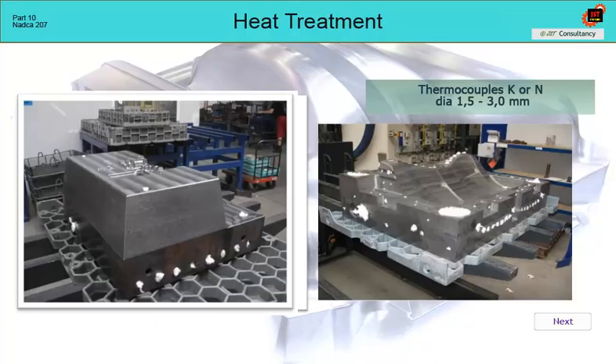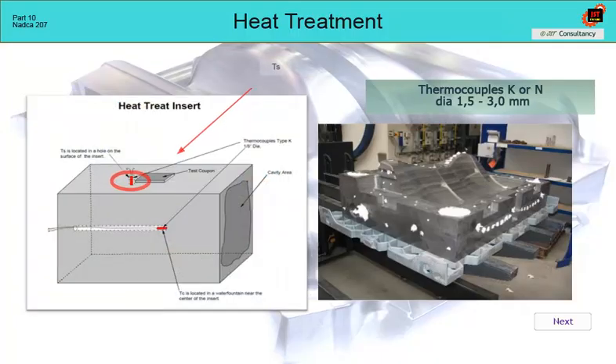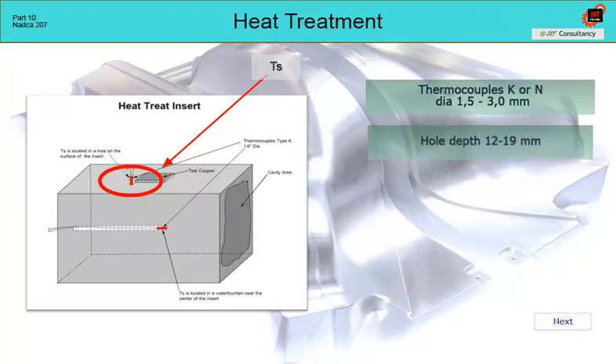The surface thermocouple should be located in the center of the back side of the insert, roughly 1/4 of the width and 1/4 of the length from the edge of the insert. The thermocouple must be inserted to a depth of approximately 12 to 19 millimeters. It should be noted here that the heat treatment plant has no possibility of making these holes for thermocouples.